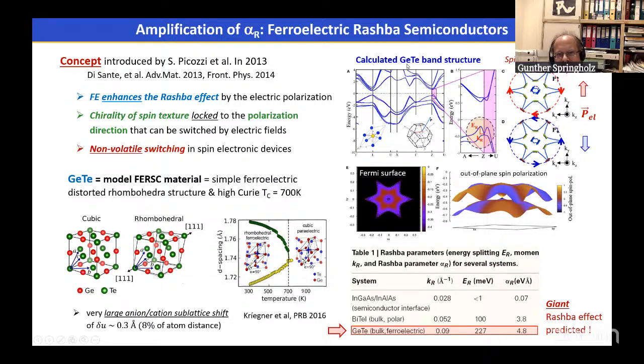So they have calculated the electronic band structure by DFT calculations. And this is shown here. The band extrema here are at the Z point of the Brillouin zone, that is at the edge of the Brillouin zone along the 1-1-1 direction, parallel to the ferroelectric distortion axis. And in this dashed circle, one can see the Rashba splitting of the valence band, as well as the Rashba splitting up here of the conduction band. They also calculated the spin polarization of the Fermi surface, which has this star-shaped form. And with the ferroelectric polarization along the 1-1-1 direction, we have the spin polarization as shown here by the red arrows. And if the polarization is reversed, the spin polarization is in the opposite direction.